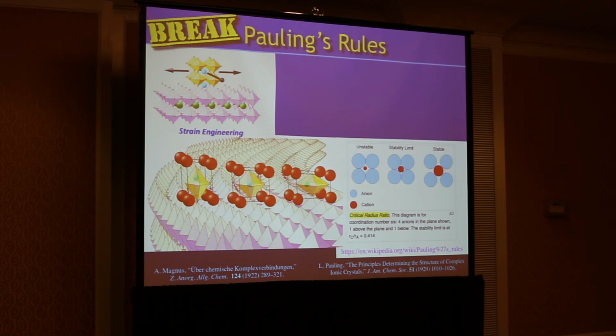Sometimes, from the luck of nature, you have such a system. But being able to engineer it by having a substrate that stretches this box. So instead of having this cage right here, imagine having a substrate that's a little bit larger than the spacing of these. That makes it so that the oxygens around this cation, I've shown here in green, you can stretch that box out. And if you stretch that box out, now it's possible for that cation to rattle around inside the cage.